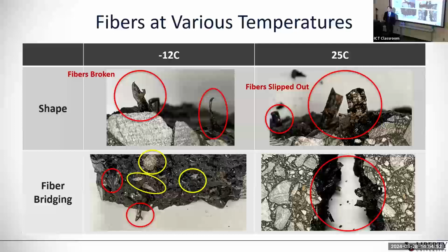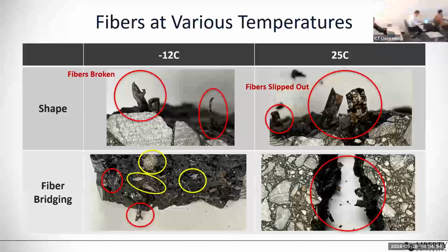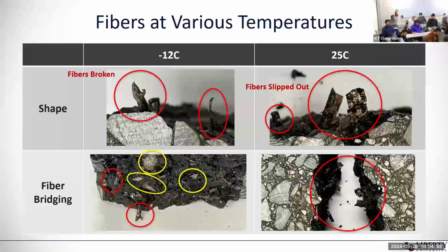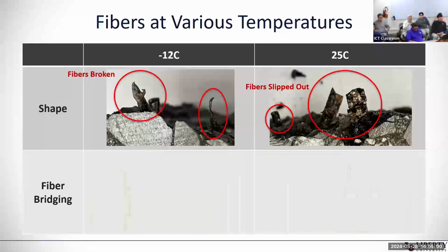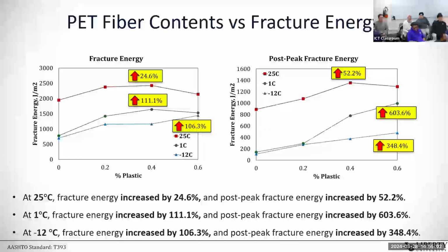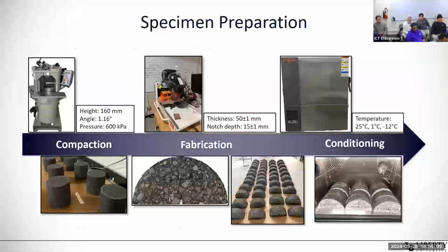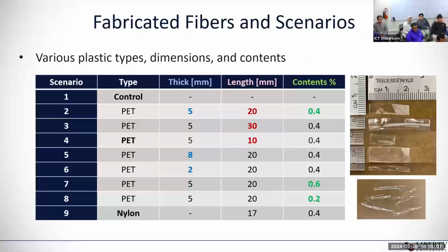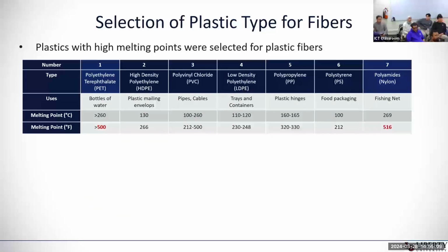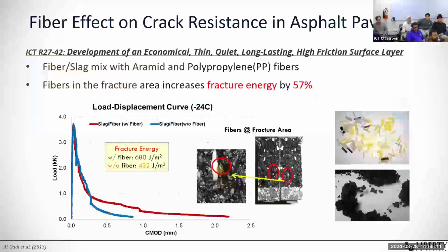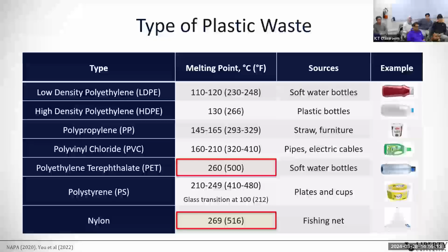Just a follow-up. I think a simpler way to think about this is to go back to the glass transition temperature slide we showed. The more we go to low temperature, the more we reach the glass state, where the elastomer changes to be more rigid or more glassy. And that explains why the fiber is broken.